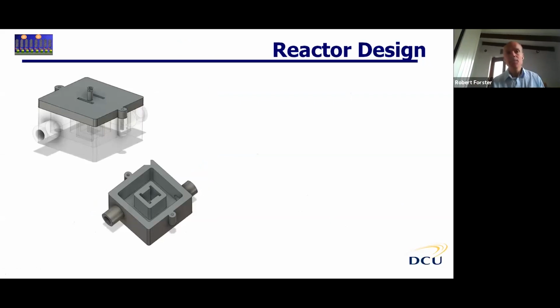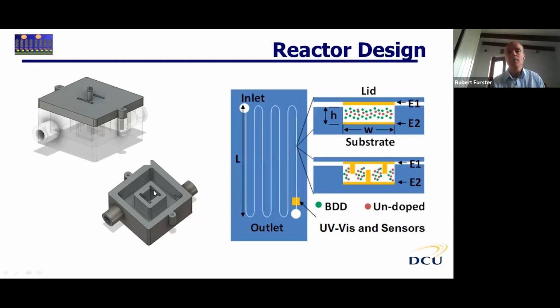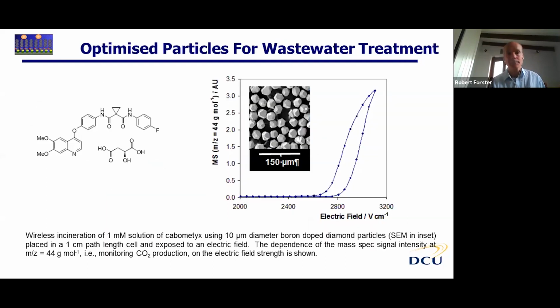So we've been designing initially simple cells. Here's the space for our two feeder electrodes, and we put a stirred suspension of the boron doped particles in here. We apply a potential to the two feeder electrodes, generating hydroxyl radicals at the boron doped diamond particles, which then decompose the organic of interest. Later on, we're hoping to persuade Stephen and Gordon to devise intricate 3D electrodes that will let us shape and control the electric field within the reactor.